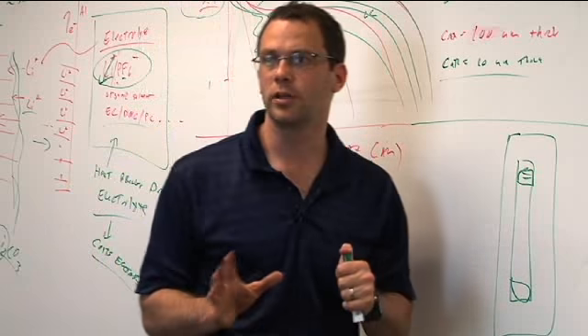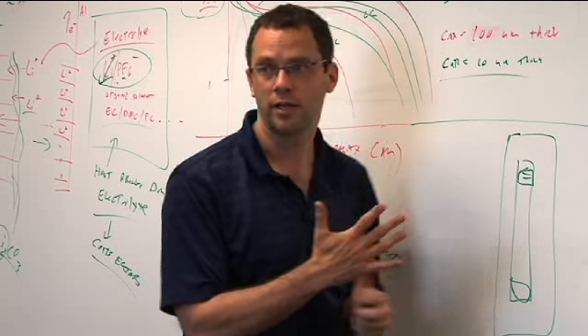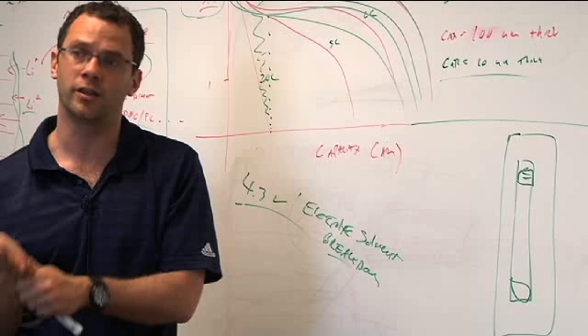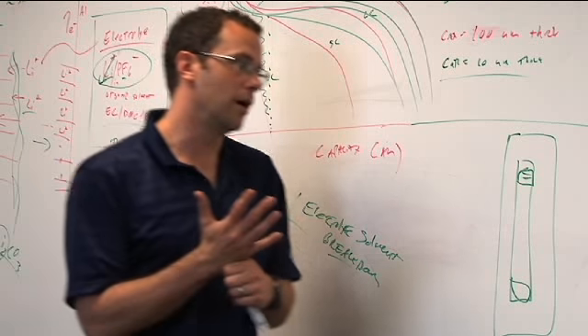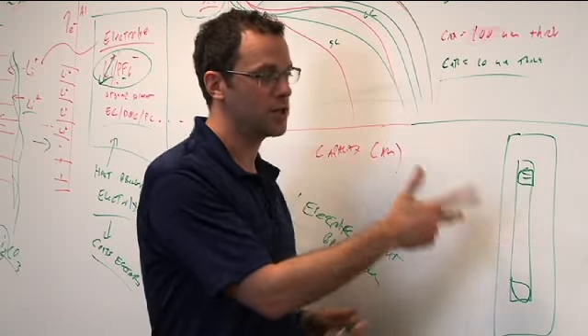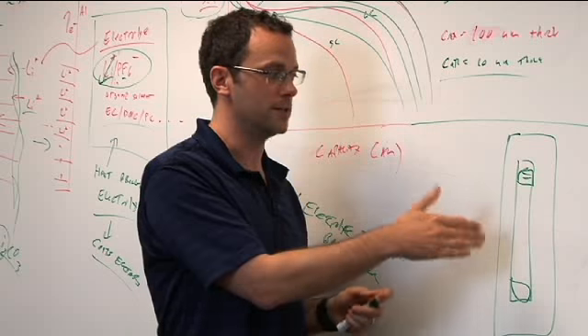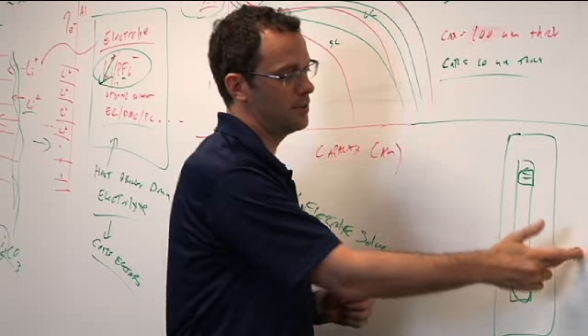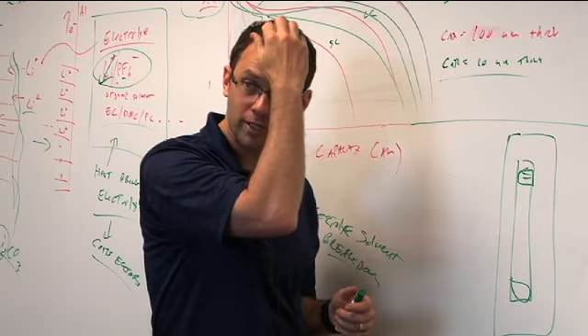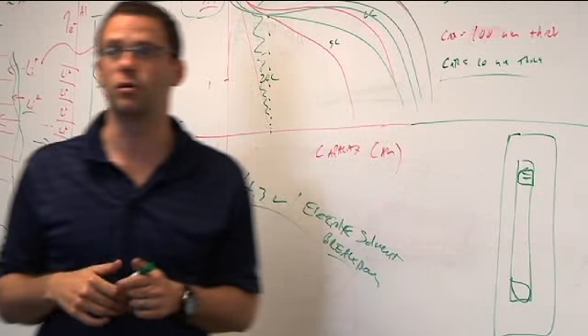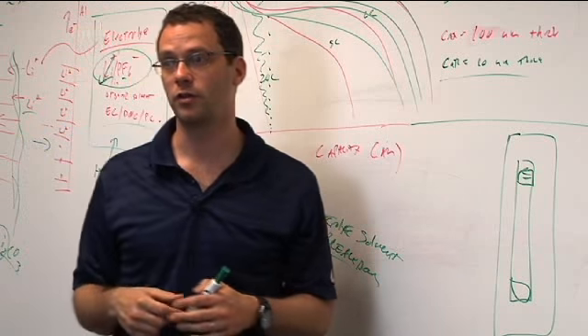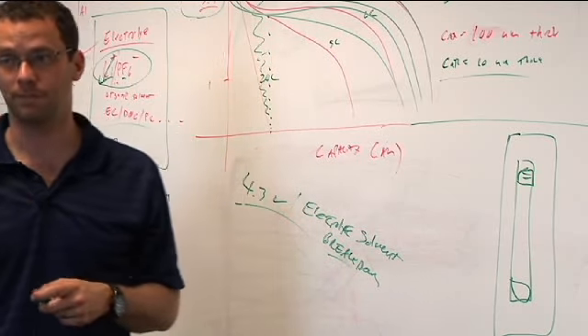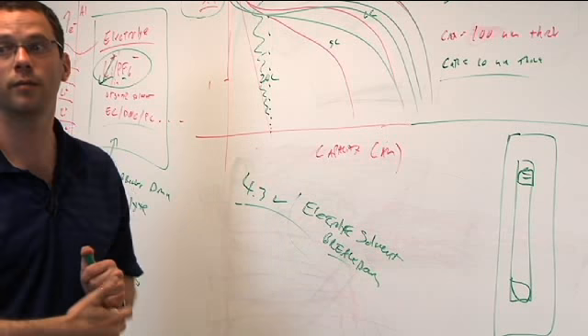Just something that's thermally conductive, that's in contact with the electrolyte inside. What you want to get to is the temperature of the electrolyte. That's what matters, okay? And that's actually an interesting thermal control question: when my heat sink is this temperature, what temperature do I think my electrolyte inside the cell is, right? So you actually want to capture both. But once you do it for a handful of cells, then you can probably just monitor the heat sink and then have the data that shows what's probably happening in the cells.